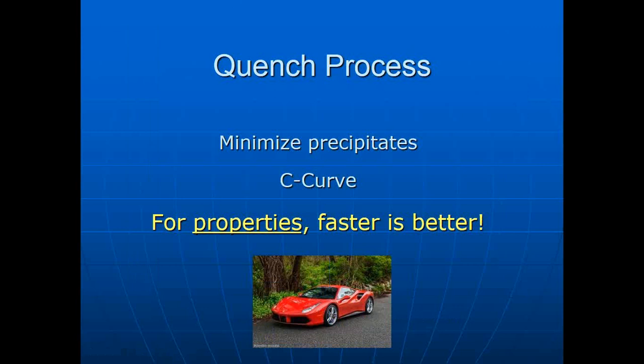For properties with quenching: faster is better. There are minimum specifications. In that case, the 6061 curve, they were specifying 20 degrees per second, or 1200 degrees per minute, as the cooling rate, but faster is better. The less the precipitation, the better the properties will be coming out of the age oven. So faster is better.